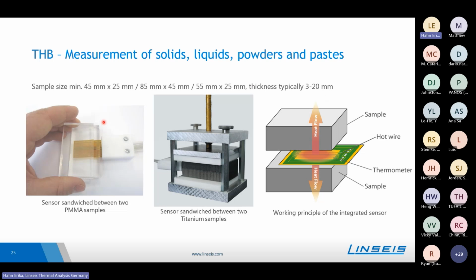For the sample preparation, in the case of solids, we need two sample pieces so that the sensor can be sandwiched in between. This means that the sensor needs to be surrounded completely by the material that needs to be tested. To improve the contact between the sensor and the sample, we compress the complete configuration, for example, with such a sample press or with a weight.